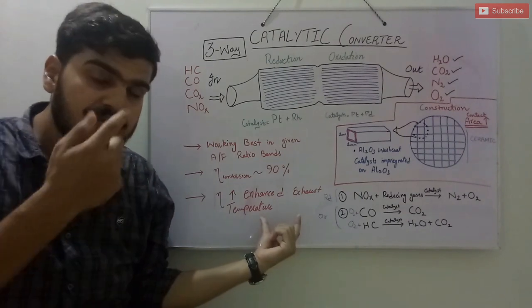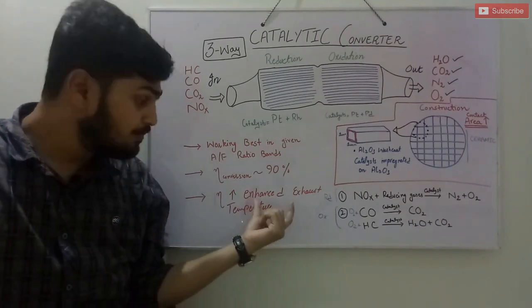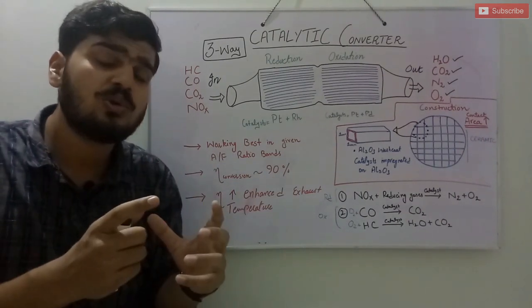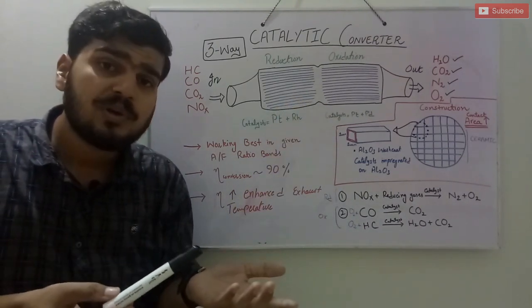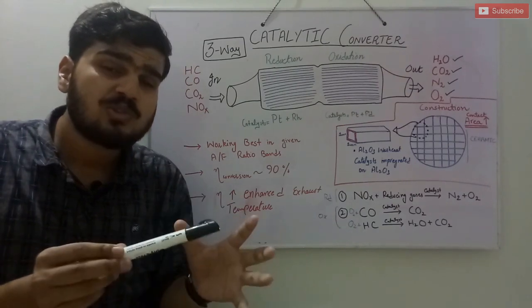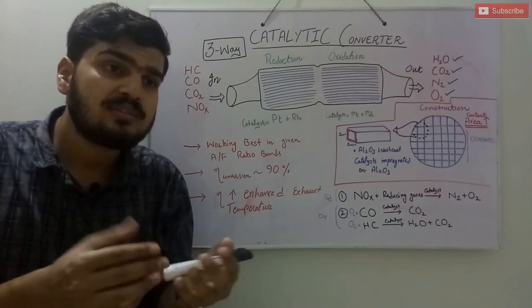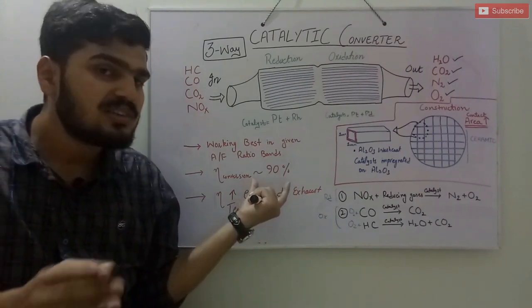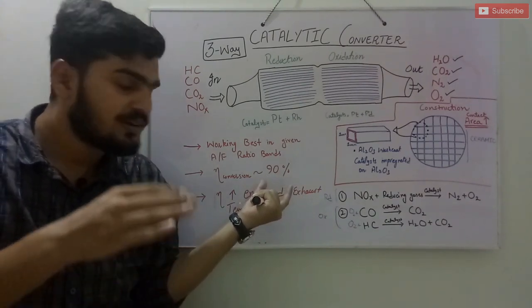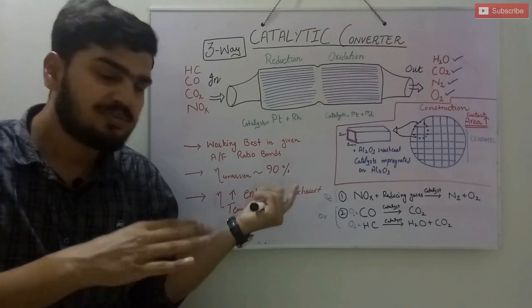The temperature factor is very important to discuss here. The temperature of the exhaust gas is really important in the working of the catalytic converter. If the temperature is not appropriate, say 200 or 300 degrees, this conversion efficiency will not be 90 percent. It will be down towards 50 or 60 percent, which is really bad for its working.